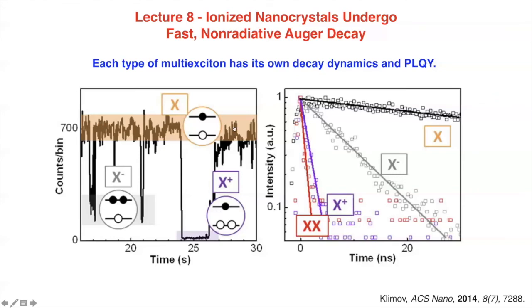And he can break the decay kinetics down. So for the very brightly emissive states, you see recombination kinetics that are slow. For the ones that are kind of intermediate, gray states, as they call them, they're faster, but still slower than the ones that are very dim. So the ones that are very dim, the luminescence barely lives at all. It's very short-lived. And so it's telling you that each of these different species here has some competing process that they can undergo that is inducing this Auger recombination.